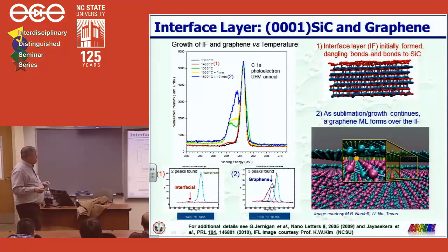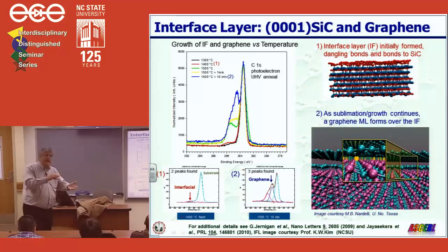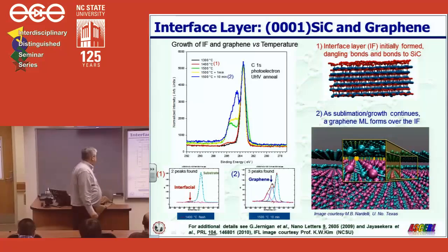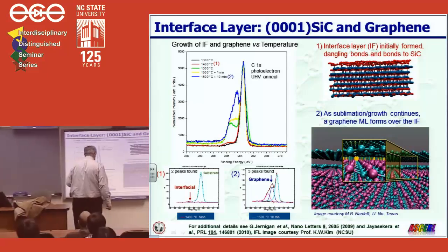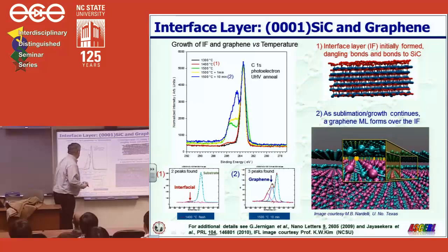Well, first, before we get to the transport properties, let's tell you a little bit about what lies underneath that graphene layer, between the graphene and the silicon carbide substrate. For the silicon polar face growth, there turns out to be an interface layer. And the experimental evidence is found by doing this progressive spectra performed by Glenn Jernigan.